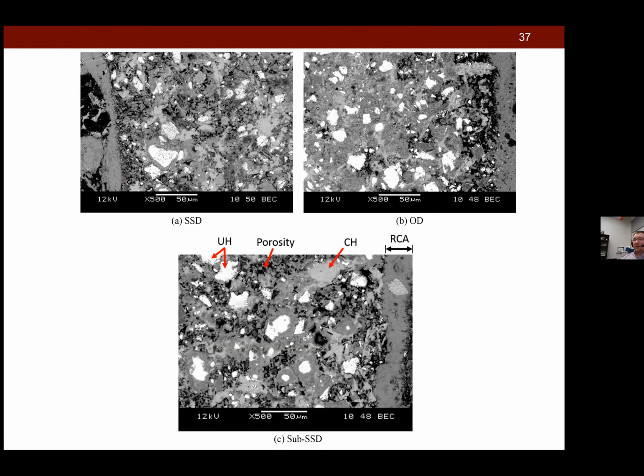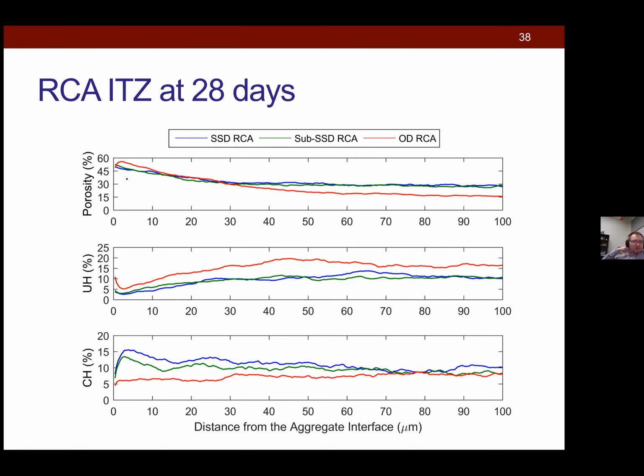All right, so here again, we can look at our microstructural cross sections. And if we look at these porosity distributions, we saw some interesting behavior. Because the oven dry RCA probably absorbed a lot of moisture, it actually locally affected the water cement ratio. So you can see we actually got less porosity in the bulk microstructure, kind of the right side of that curve. That would tell us that we're actually improving the bulk microstructure. But look at the difference between the bulk and immediately near the aggregate interface. There's a pretty big porosity difference there, right? And that's going to cause problems.